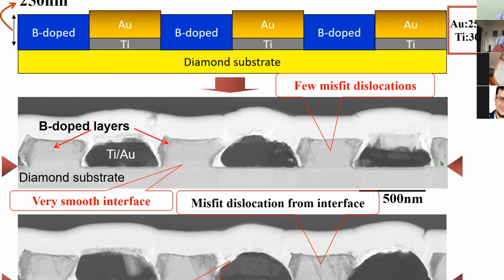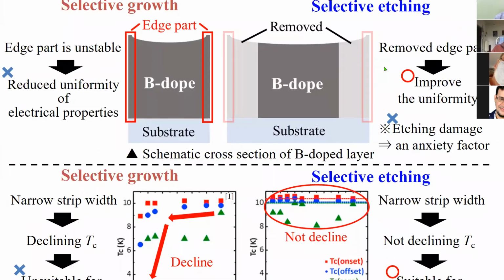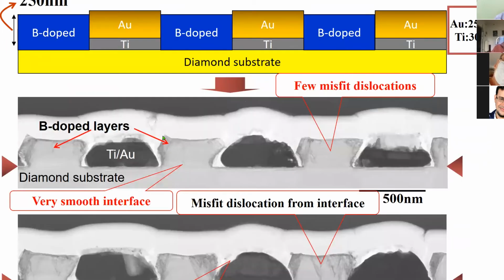Another case is to make etching, but etching is better because with selective growth, as you can see, the edge part becomes like an overhang structure. These layers are non-superconducting regions, so we don't get better quality junctions, Josephson junctions. That means we cannot make a good SQUID from this, it looks good but not for a device.